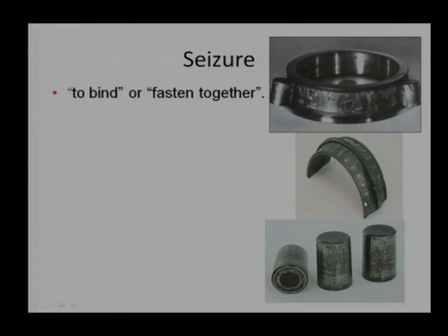Here there is another example shown, the inner ring, in two halves, of a bearing with rollers. You can see there is material being plucked out of the inner ring. There are patches and parallel patches. That means these rollers were spaced. Otherwise, we would get a continuous layer of material removal. But we know rollers are generally kept in cages and they are equally spaced. That is why we are getting equally spaced patches on the outer surface of the inner ring.